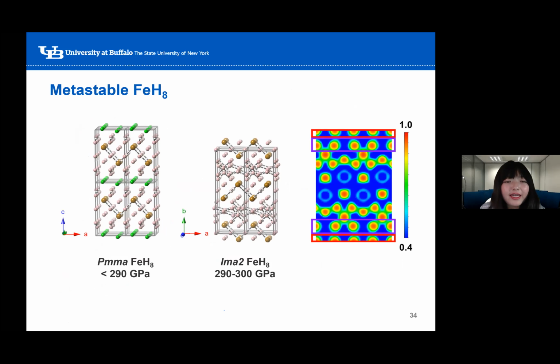For FeH8, we found the Pmma structure being stable up to 290 GPa. This structure is interesting because it is comprised of layers with iron zigzag chains and atomic hydrogens. This layer can be constructed by removing atoms from the FeH3 layers. And then the zigzag layers are separated by atomic hydrogen layers. At higher pressure, it transforms to an Ima2 structure, which is also comprised of zigzag layers, but in AB stacking. And the atomic hydrogen layers form a unique X motif.